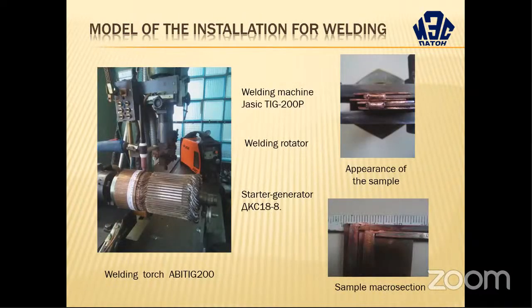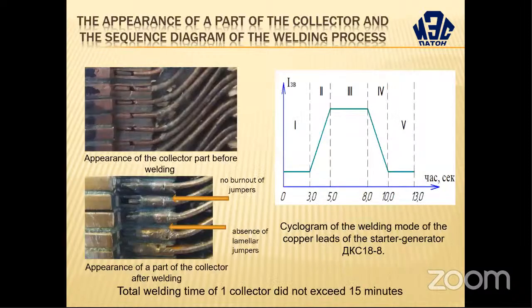Welding in the prototype starter generator was performed in the installation layout, which is shown in the picture. The armature was fixed in a rotator on roller supports in a horizontal position. The torch was mounted locally above the welding area in a device that allowed it to move along the collector lamella in the range of ±5 millimeters. The picture shows the appearance of the full-scale sample after welding. The collector section before welding and after welding is shown in the picture.